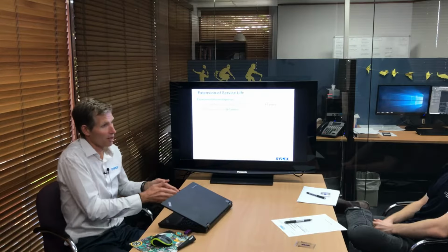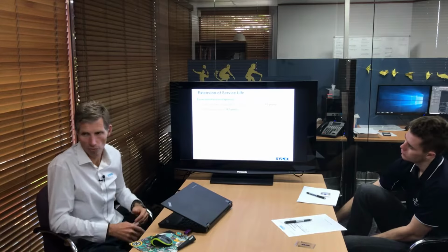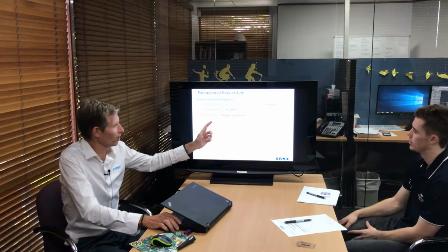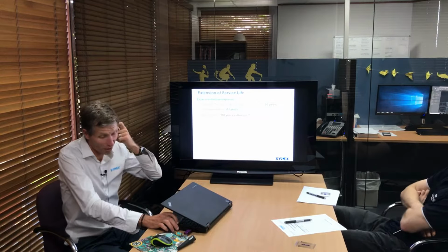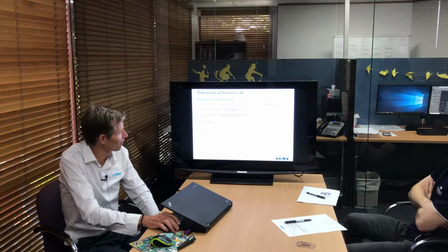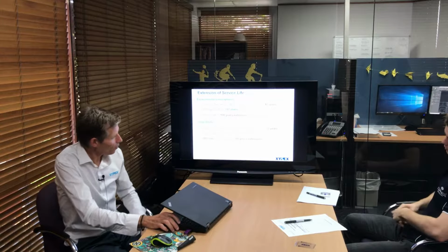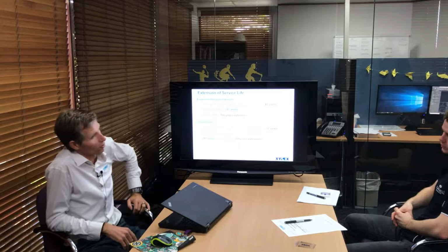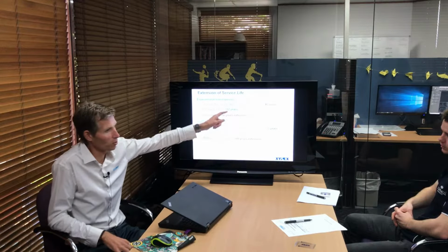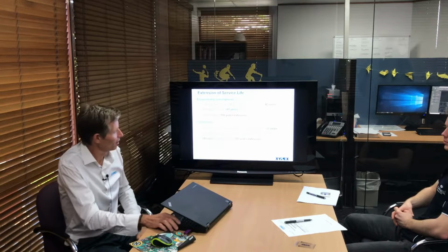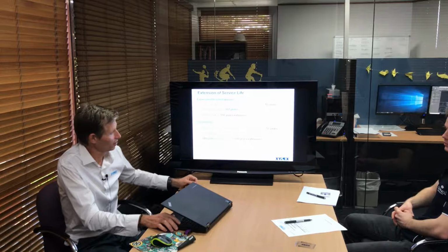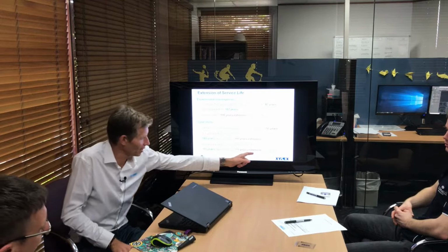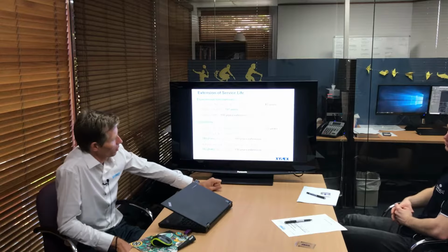With the addition of Xypex Admix in this controlled lab environment, they had the forecast there of 147 years. So when you then go back and cross-correlate it, we really are able to clearly exhibit both in the field and in the lab that you've got 100 years extension of service life in that type of environment. So comparing that to the case study in Cronulla Marina, take your 19 years and add your 129 onto it, 148 years. So once again, that's almost identical to your test environment, but bearing in mind that's at a reduced cover. When you put it into context with Australian code and the appropriate cover, you're actually seeing that type of extension. So you're looking at about 130 years worth of extension of service life.